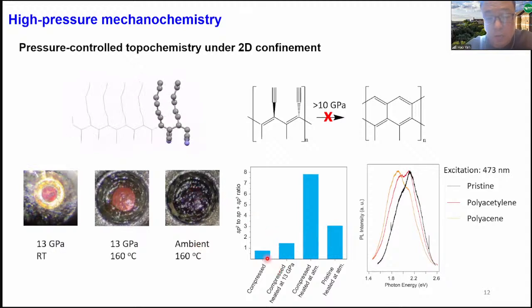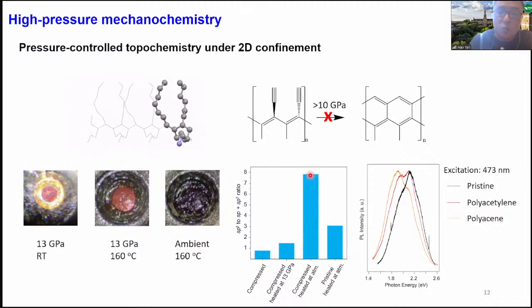You can also see this from the relative content of the sp2 carbon: at high pressure and high temperature, not much change. But if you release the pressure and heat it, then all of a sudden the sp2 carbon amount increases by a lot. So what we think happens here is this.